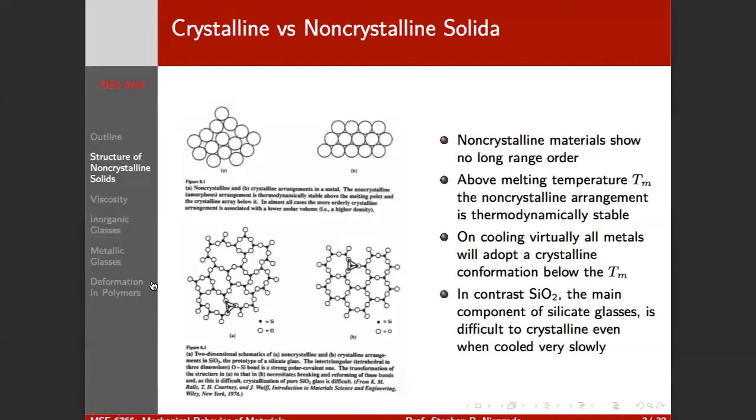And that's the other frustrating thing when we talk about amorphous materials. We're often talking about metastable structures. They're kinetically frustrated structures. They're not at their thermodynamic equilibrium. So that means we can't fall back on some of the thermodynamic arguments that we can make in crystalline materials.